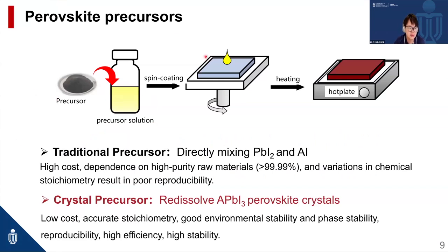For the perovskite precursor, the traditional precursor uses a lead iodide and ammonium iodide mixture. If we need to fabricate high efficiency, we require higher purity raw materials, such as lead iodide. This will increase the cost of the precursor price, and then the varying stoichiometric ratios will result in poor reproducibility.